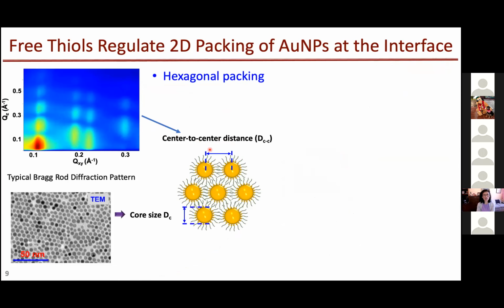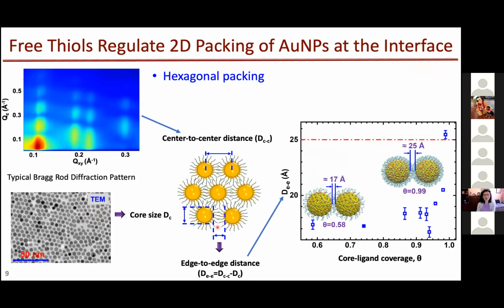It tells us that the nanoparticles form hexagonal order at the interface, and from the diffraction pattern we can determine the center-to-center distance and the core size. The core size can also be directly obtained from TEM image, so from there we can deduce what we call edge-to-edge distance, which can be compared with a fully extended thiol length.